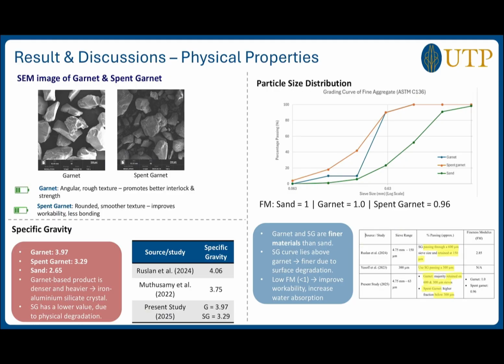And for spent garnet, it has lower specific gravity compared to garnet because of the physical degradation of the post-use. And this table is the comparison of previous research and my research. And the third one is particle size distribution. So from the graph here, we can see the orange one is spent garnet, blue is garnet, and the green one is sand. And from this graph, we can see garnet and spent garnet curve lies above sand curve, showing that it is finer than sand. And for the spent garnet, it lies above garnet curve, showing that it is finest material among these 3 because of the surface degradation of the post-use.